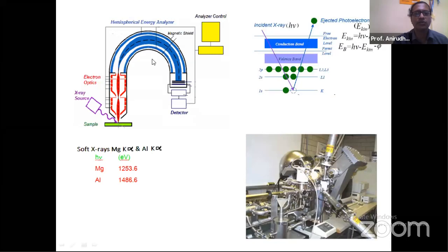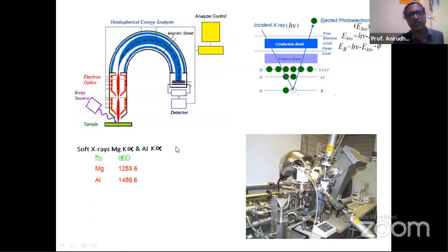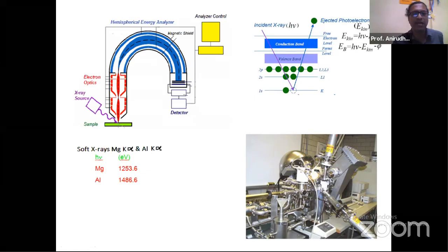So this shows a small diagram on the top left-hand side of this slide, where I have shown an X-ray source. There is a sample, and below that I have written soft X-rays, basically from magnesium K alpha radiation and aluminum K alpha radiation. Mostly these are the two popular sources used: the magnesium K alpha X-ray source and the aluminum K alpha X-ray source, and their energies are, for magnesium, close to 1253.6 electron volts, and for aluminum 1486.6 electron volts.